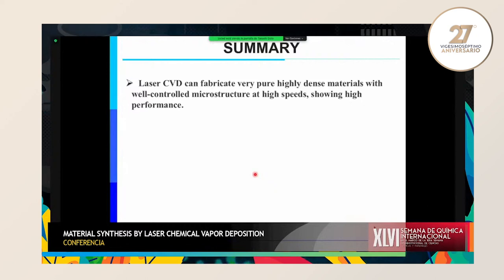Self-orientation in crystal growth doesn't get affected by the substrate. So the material has its own habit to grow in some specific directions. At some conditions, a material, for example silicon carbide, wants to grow in the 111 direction at high temperature, or it depends on the gas concentration or pressure. It depends on what kind of atmosphere and temperature.